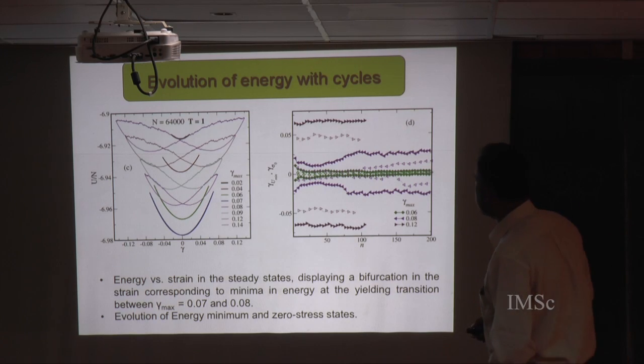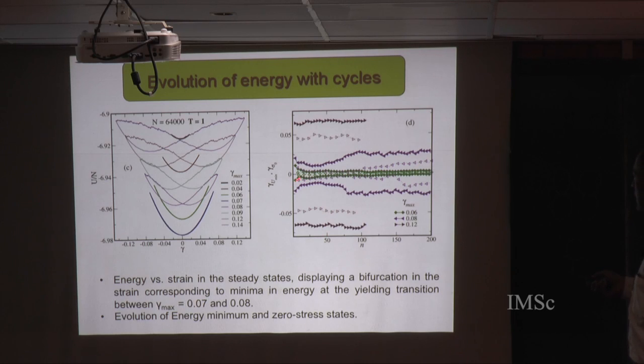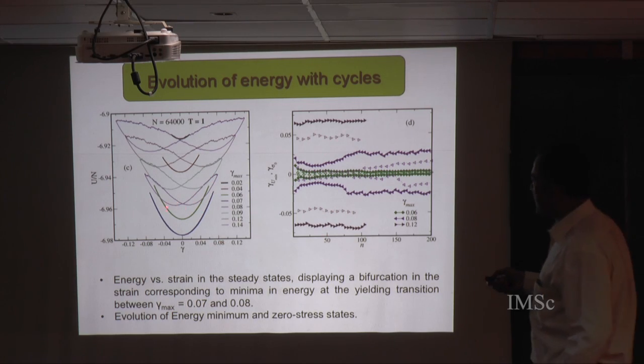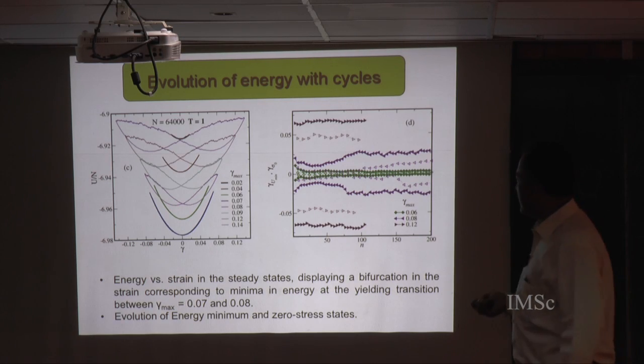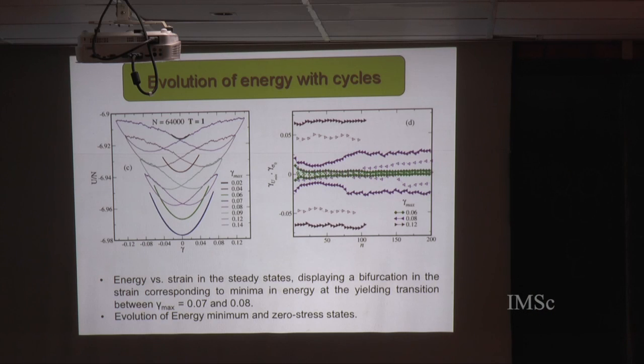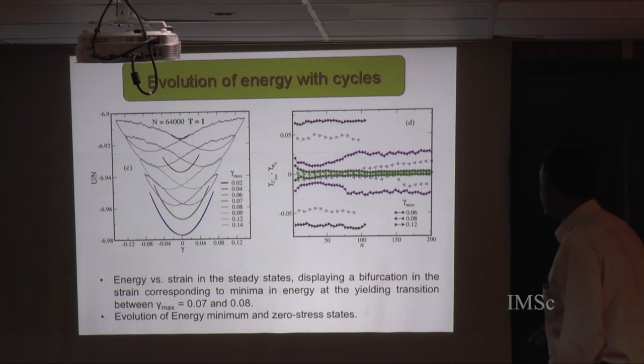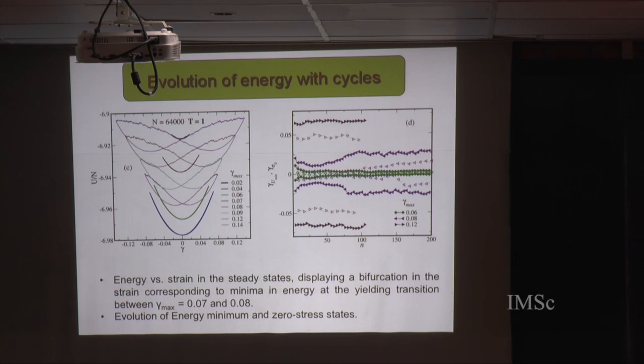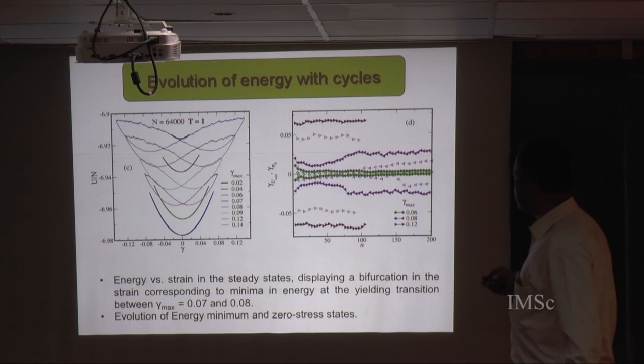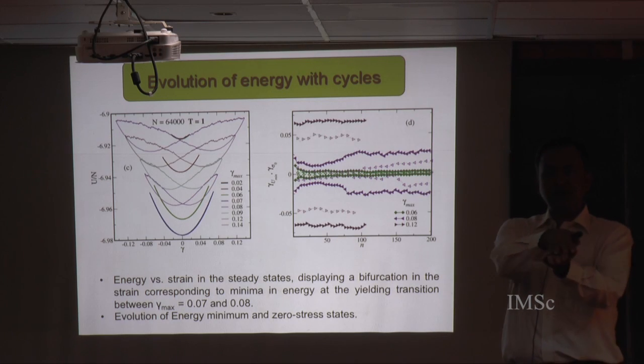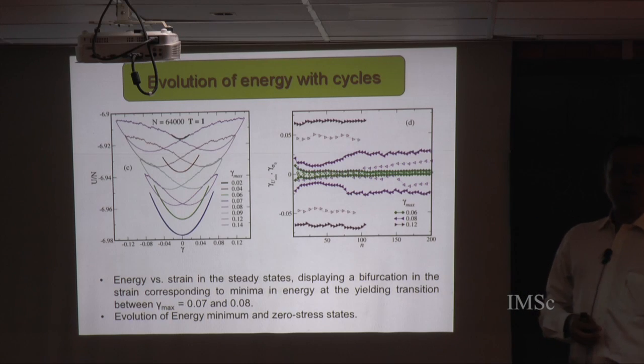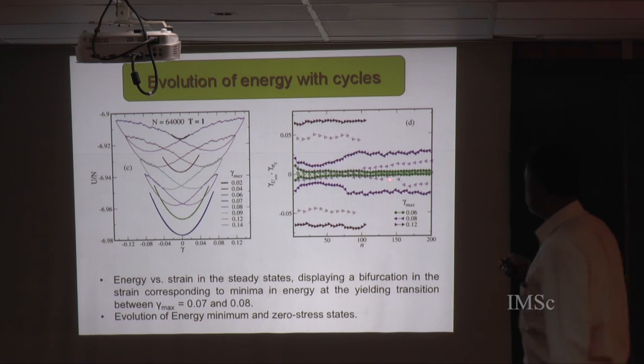It's also interesting to see what happens to the strain values at which the energy is minimum, as a function of the number of cycles. For the data I show here, the most interesting thing is that when I'm sitting below the yield point, even if I start with some initial configuration where the minimum energy is at some finite strain value, that finite strain value gets annealed out, so eventually I converge to a state where the zero strain configuration is the one with the lowest energy.